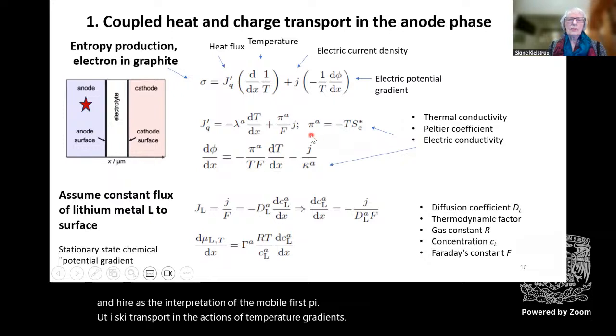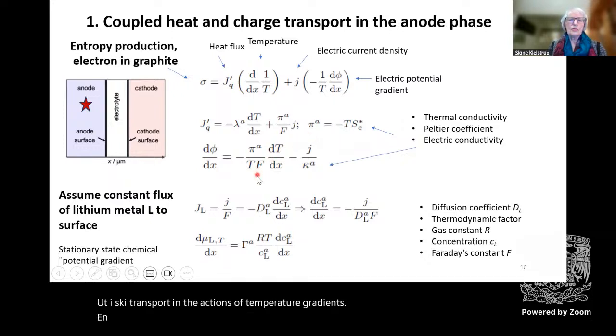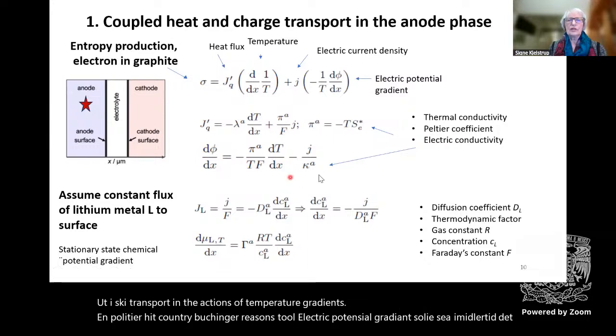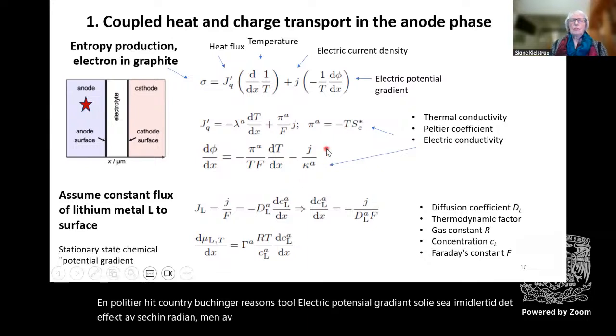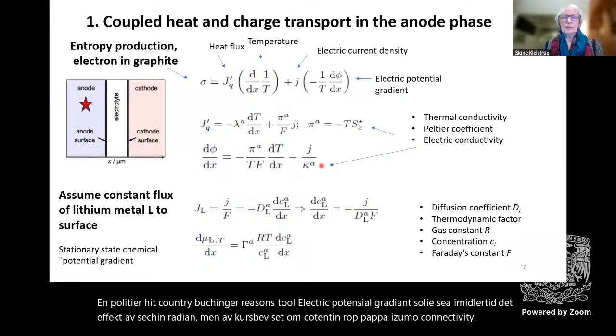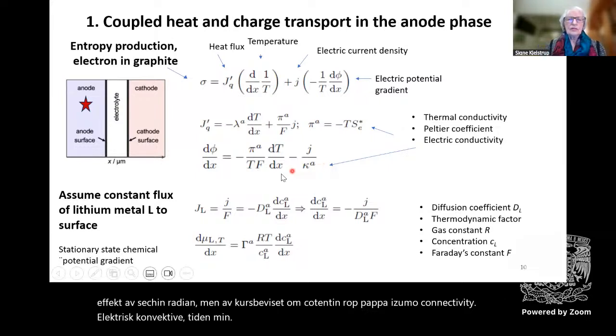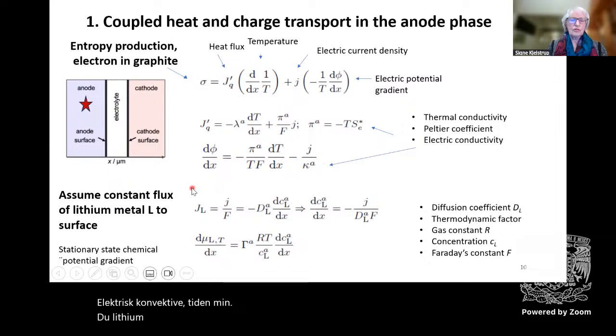And the Peltier heat contributes for symmetry reasons to the electric potential gradient. So you see immediately the effect of such a gradient. And of course, there is an ohmic potential drop. Kappa is the electric conductivity, I mean. The lithium metal moves to the electrode interface here, where the reaction takes place. It moves as a metal.